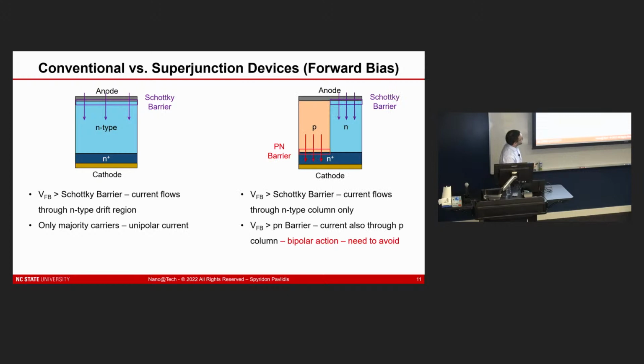In the superjunction case, you now have 2 regions, and basically 2 important barriers to think about. One is going to be that top metal semiconductor barrier, which is that same Schottky barrier over here. And then you have another p-n junction down here. So the idea is to be able to turn on your device, or engineer that Schottky barrier to be somewhere below that p-n junction, and then still get high current flow with low turn-on voltage or low forward voltage drop to keep your efficiencies high as well. And we want to avoid getting into the p-n junction regime where we have bipolar action happening.